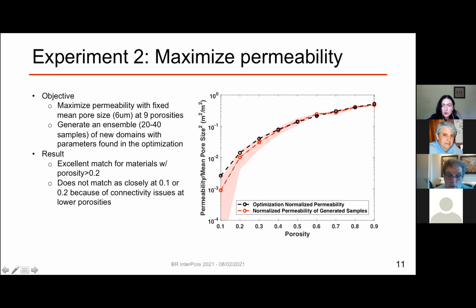The agreement between the target and what we were able to achieve is not as good at 0.1 and closer to 0.2. And the reason for that is that the optimization scheme solves for shape parameters at maximum permeability. And we have a specific set of kernel locations and kernel orientations. So when you have very small porosity, fixing the kernel locations and orientations means that the connectivity is difficult to optimize. So we're limited in the optimization. But at higher porosities, like on most of the samples that we were able to generate, the connectivity is not as sensitive to where those kernels end up when we throw them in the domain. So that is the reason why we were able to achieve much better results at porosities of higher than 20%.